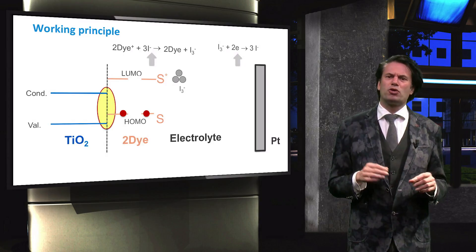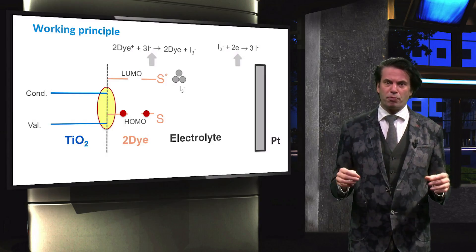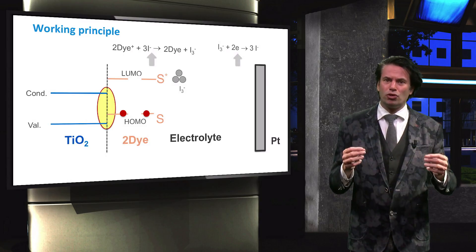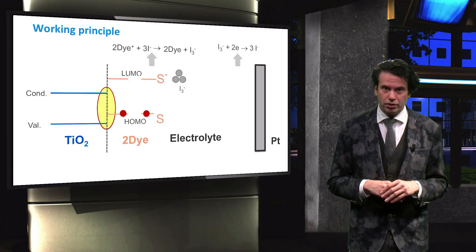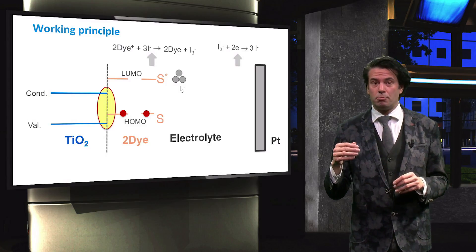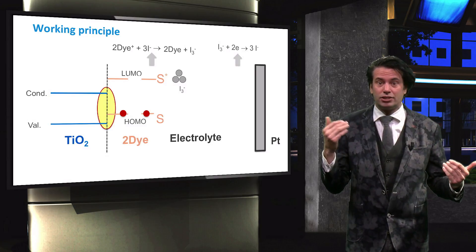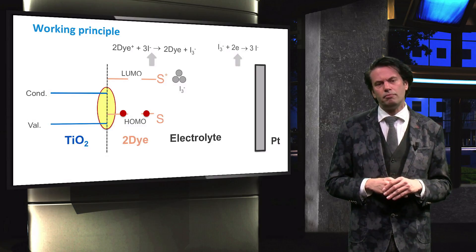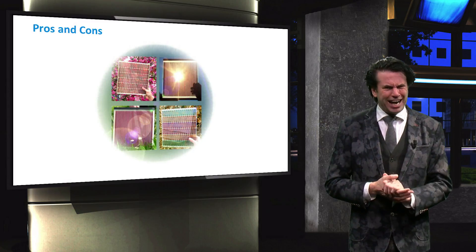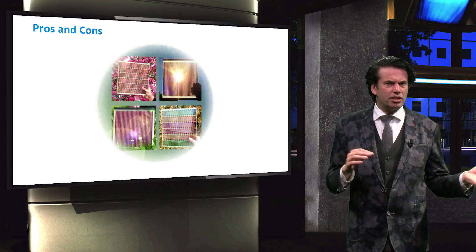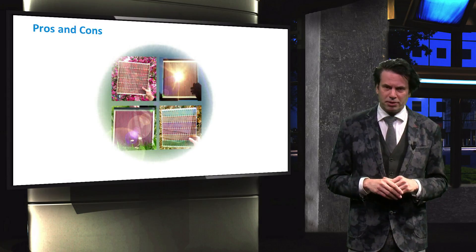To facilitate the redox reaction, these photoelectrochemical cells require a platinum back contact. As a result, the performance of a dye-sensitized solar cell depends on the HOMO and LUMO level of the dye material, the Fermi level of the titanium oxide nanoparticles, and the so-called redox potential of the iodide and tri-iodide reactions. The current certified record efficiency of a dye-sensitized PV device on lab scale is 11.9%, achieved by Sharp in 2011.